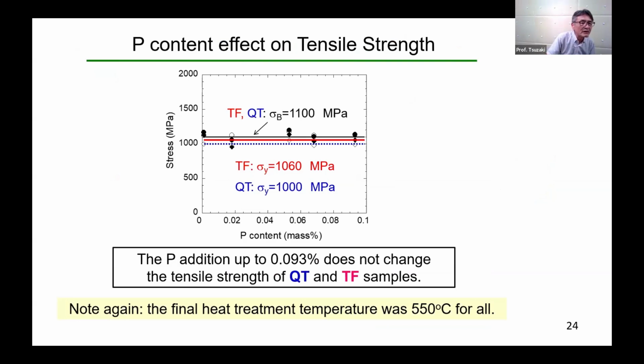Next, phosphorus content effect on tensile strength is shown here. Stress and P content. The P addition up to 0.093% doesn't change the tensile strength of QT and TF sample both like this. It is reasonable since the microstructure isn't affected by P doping, as I said in the last slide. Note again, the final heat treatment temperature was 550 degrees Celsius for all.